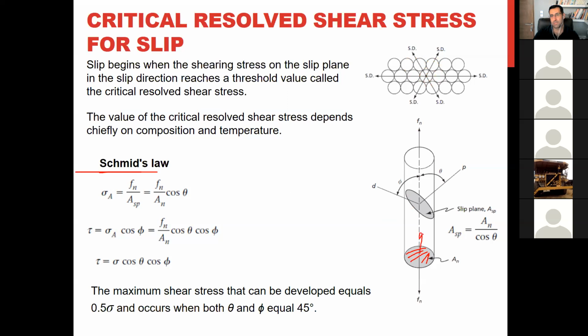and you're applying load like this, nothing happens, because you're applying tensile stress normal to a slip plane, and as your shear stress is zero, there is no slip there. Or if you apply this load parallel to this plane, which is a slip plane in this direction, again you cannot deform it by slip, because you are applying load parallel to the plane, and these planes cannot slip on each other. So we must have an angle.